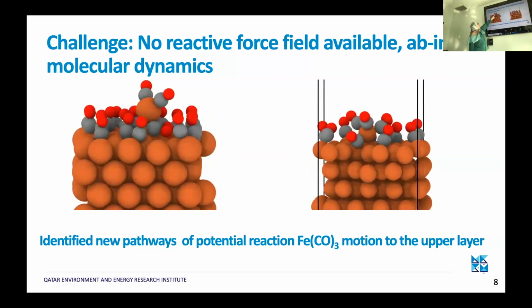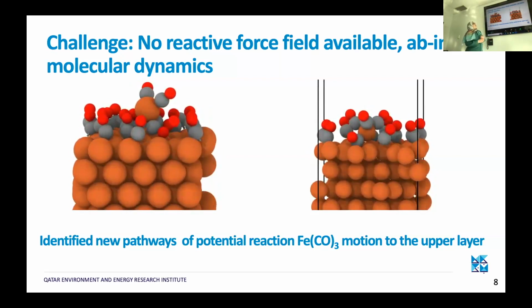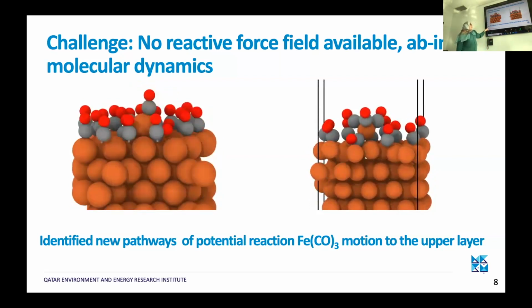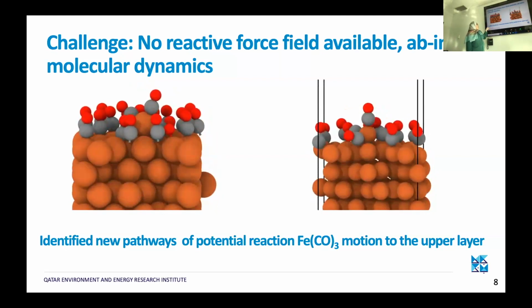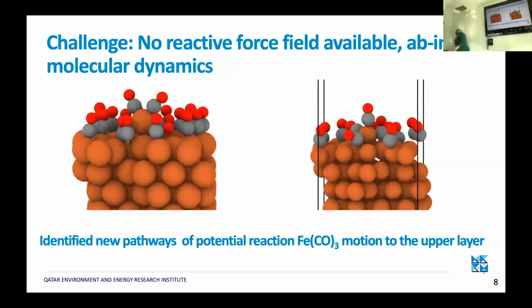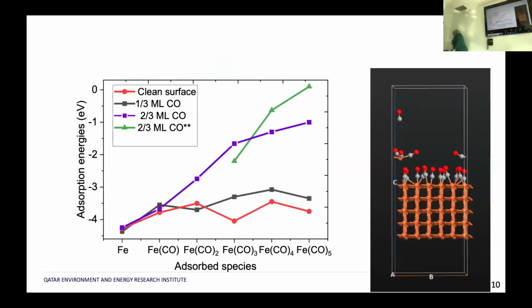In this case, the iron atom here is already bound with 3 CO molecules. So actually, what we did is we said, okay, now maybe there is another phenomenon that we can account for, and we took that configuration, started from Fe(CO)3, and started to add CO molecules. You see that in terms of adsorption energy, we reached a point where adding the next CO molecules led to the desorption of the pentacarbonyl molecule.